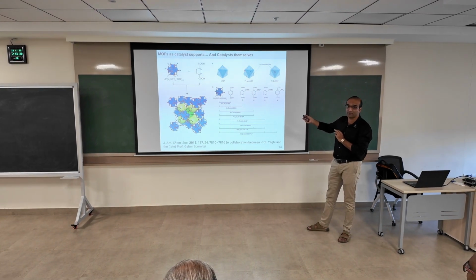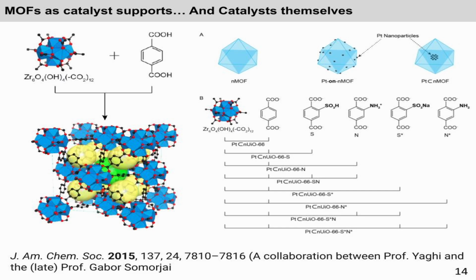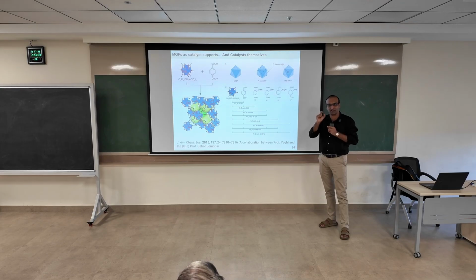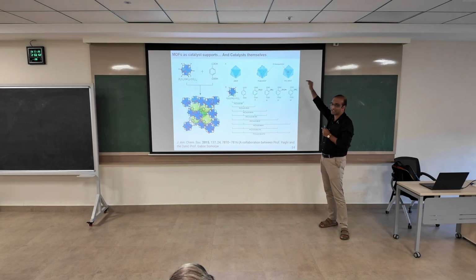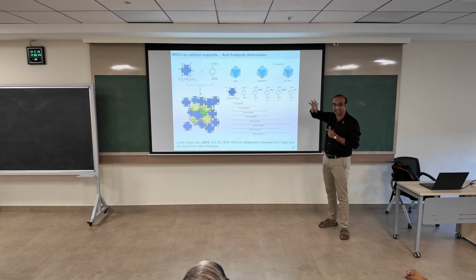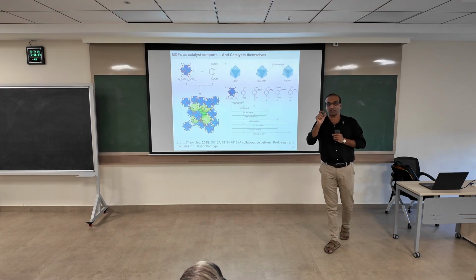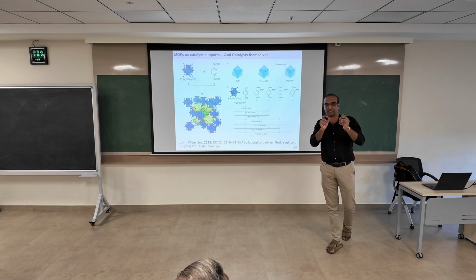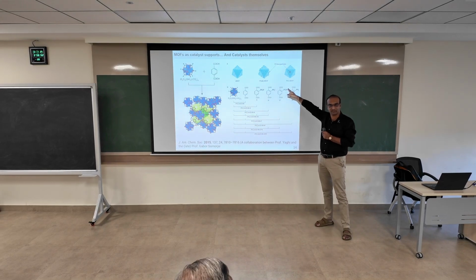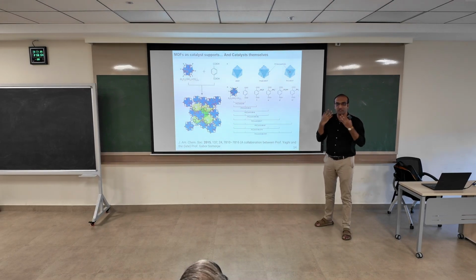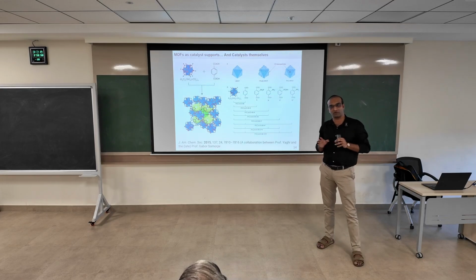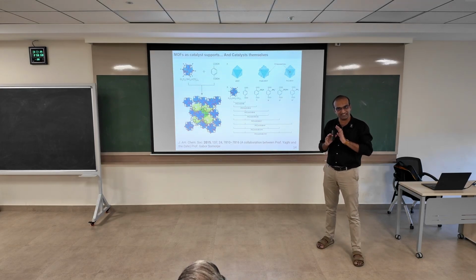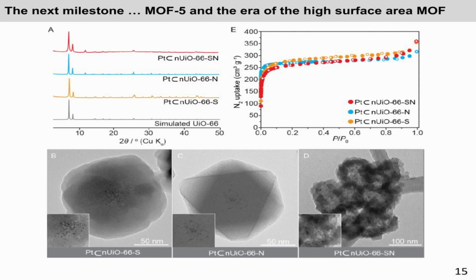There's a difference between putting the platinum outside and inside; I've shown you a bit why it's important to put the platinum inside the MOF, okay? Because this MOF network can also form a restricted environment. If you want a particular reaction to happen selectively, the particle has to be inside because the whole MOF is acting as a gate to what kind of bonds or what kind of moieties on the organic substrate can access the catalyst, the actual catalyst, okay? If the platinum is outside, it's just going to hydrogenate everything. Platinum is a very well known catalyst industrially, but it doesn't have any selectivity. If you put any molecule on it, it's just going to break it, and I'll show it to you in a bit. So yeah, this is a typical MOF.